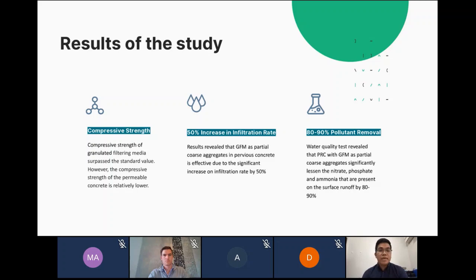After performing all experiments and tests, these are some of the highlights of the results of the study. First, it was concluded that the compressive strength of the granulated filtering media produced from three known waste materials surpassed the standard value. However, the compressive strength of the permeable concrete produced is relatively lower compared to the standard value. However, in terms of infiltration rate, results revealed that the granulated filtering media as partial coarse aggregates in our pervious concrete is also effective due to the significant increase in infiltration rate by 50%.